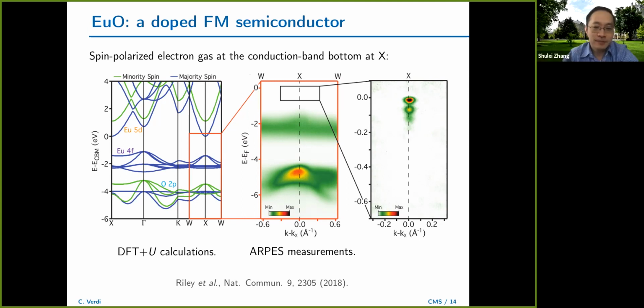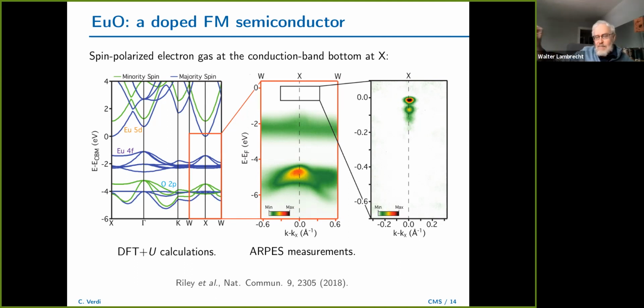Okay, thanks. So while we have this picture up, were you telling us here that these plasmon-related peaks were related to the higher conduction band, which has the opposite spin? In practice, spin doesn't really play a major role. We need to take into account that the bands are spin polarized, but that's it. The fact that it's a spin polarized electron gas doesn't have any major physical implication, apart from obviously changing the occupancy of the bands, because the spin splitting is large enough that it doesn't really play a role. Yeah, I see now. I missed the scaling.